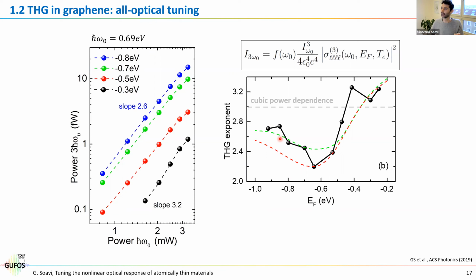So what is interesting is that if we had a material where sigma 3 was independent of the electronic temperature, then all these points would be scattered around 3, so around a perfect cubic dependence. Instead, since sigma 3 depends on the temperature and the temperature depends on the input power, we have this very peculiar behavior in the third harmonic power dependence.